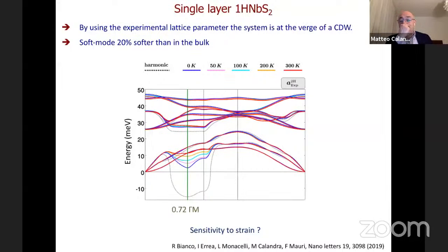In the single layer, if you use the experimental lattice parameter, the system is much closer, at 0 Kelvin, even including anharmonicity, to a charge density wave instability. You see the phonon frequency is very, very small, 2 or 3 meV after anharmonicity. On the contrary, at the harmonic level it is very imaginary, and the periodicity is different, because the Q is about 0.72 along gamma-M, that is very close to a 3x3, which is actually seen in the bulk. So what does it mean?